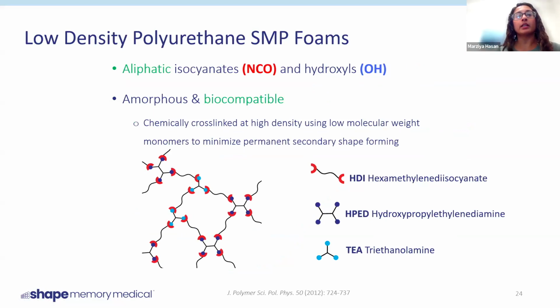Our foams specifically, we decided to use all aliphatic isocyanates and hydroxyls, and that's motivated by the medical application. We don't want to use any aromatics because that's where things tend to go wrong. That's typically what has gone wrong in the past when people have used aromatics in medical applications specific to polyurethanes. And then our material is amorphous and biocompatible per the various biocompatibility studies that we've done.